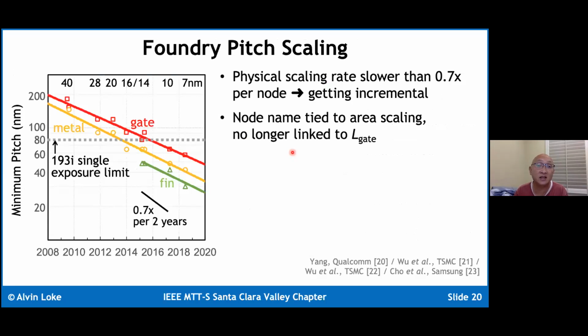So foundry pitch scaling obviously has been key. You can't talk about scaling without lithography. But if you look at, for instance, how the minimum pitch, the center to center separation between two features, has been scaling through the years with technology node, you can see that the physical scaling factor has been less than what we've historically enjoyed, about 0.7x per 2 years, or on an area basis, 0.7 squared, or about half per 2 years, okay? And so the physical scaling has actually been getting increasingly incremental over the years.